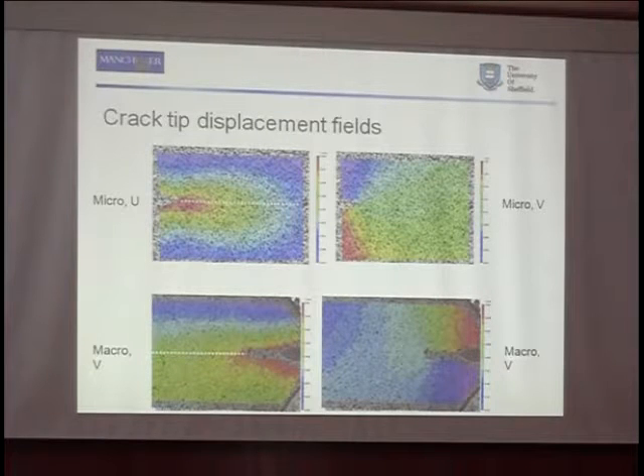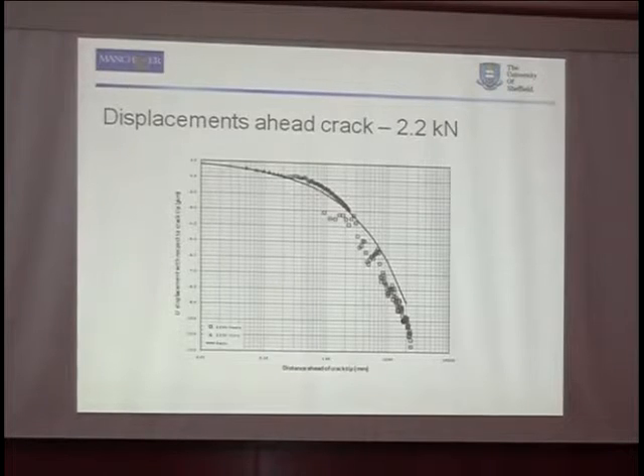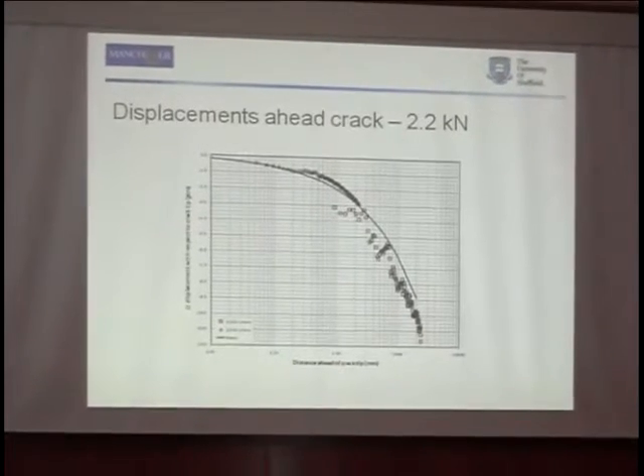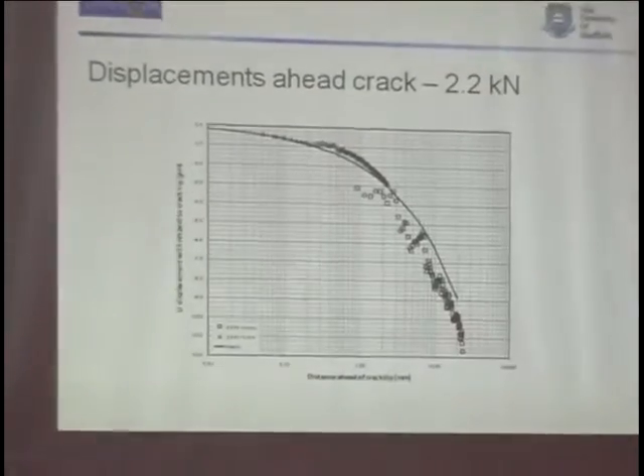So what we did then was a preliminary investigation. We extracted displacement fields along in the U direction, and horizontally along those 2 white lines, just to compare that with linear elastic predictions. And that's for the 2.2 kilonewton crack. So, apart from very near the tip, most of it is fairly elastic. You can see that the data agrees quite well with the linear elastic fracture mechanics predictions. Whereas for the 4.5 kilonewton crack,